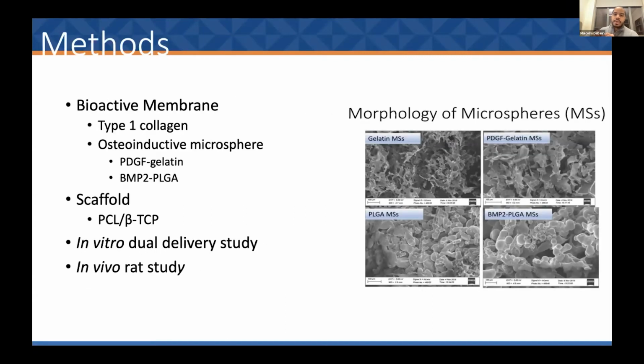So we first created different microspheres that have osteoinductive growth factors that basically stimulate cells to produce bone. So we had a bioactive membrane made of type 1 collagen and put these different microspheres that contain growth factors into them that degrade over time. And then we put that membrane that was synthetically created around a scaffold that has some strength and compression. And again, this is a 3D printed scaffold. And then we first tested it in an in vitro model to determine if the growth factors would release in a controlled fashion over time. And then we tested it in an in vivo rat model.